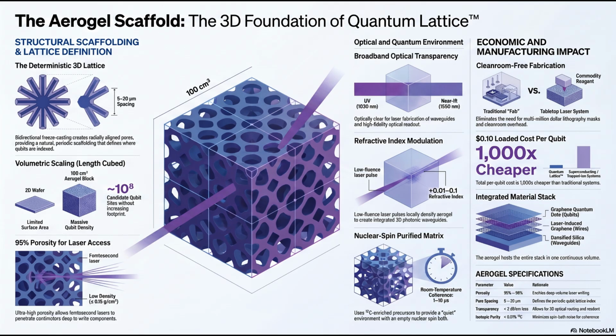To mitigate this, they outline an optional chemical step: carbon nanotube, or CNT reinforcement. So they are basically putting microscopic rebar in the concrete. Essentially, yes. By incorporating ultra-strong carbon nanotubes into the initial sol gel formulation before freezing, the nanotubes weave themselves through the silica framework. It dramatically increases the tensile strength and the thermal shock resistance of the matrix. So it holds it all together. Right. This allows the block to survive vacuum environments, mechanical vibrations on the laser stages, and the extreme thermal cycling of a cryostat. Okay, so we've solved the fragility problem.